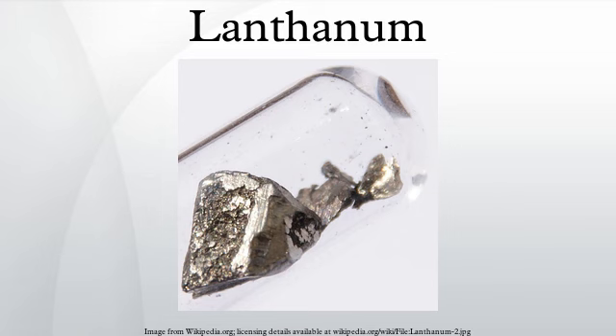Lanthanum metal is obtained from its oxide by heating it with ammonium chloride or fluoride and hydrofluoric acid at 300 to 400 degrees Celsius to produce the chloride or fluoride: La2O3 + 6NH4Cl → 2LaCl3 + 6NH3 + 3H2O. This is followed by reduction with alkali or alkaline earth metals in vacuum or argon atmosphere: LaCl3 + 3Li → La + 3LiCl. Also, pure lanthanum can be produced by electrolysis of a molten mixture of anhydrous LaCl3 and NaCl or KCl at elevated temperatures.